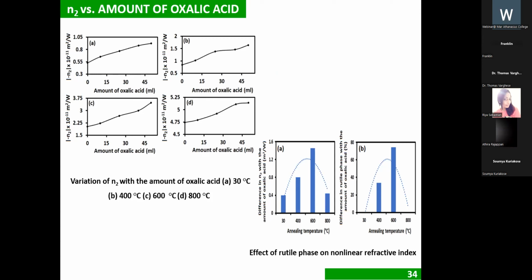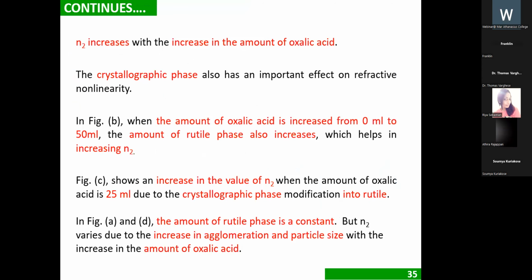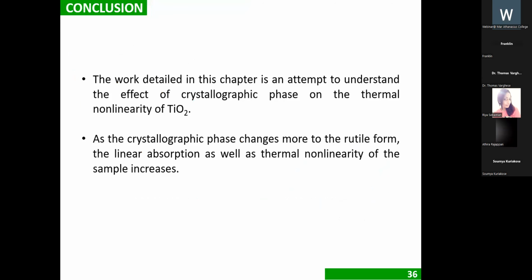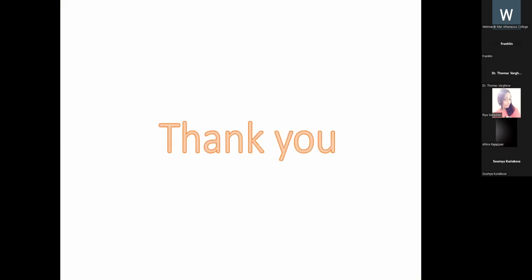The rutile phase effect can be mainly observed at 400 and 600 degrees Celsius, where the change to the rutile phase of TiO2 from other phases can be visible. Then the conclusion: the work detailed is an attempt to understand the effect of crystallographic phase on the thermal nonlinearity of TiO2. As the crystallographic phase changes more to the rutile form of TiO2, the linear absorption as well as thermal nonlinearity of the sample increases. That's all. Thank you.